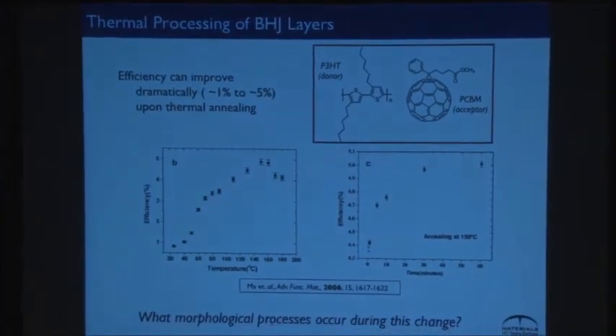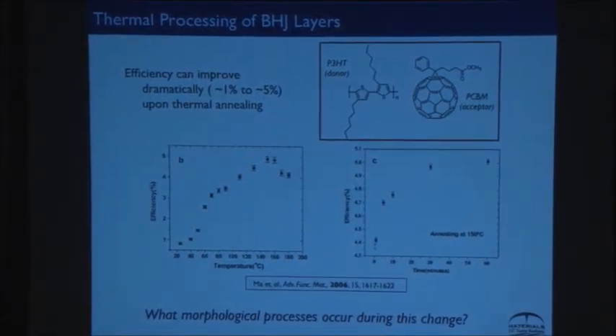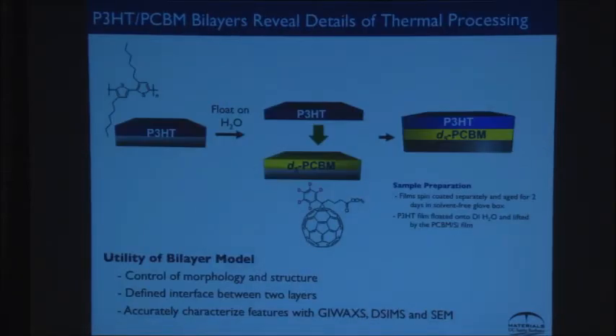For a long time, people argued about this, and they said, well, this material is crystalline, this one's not, maybe this one needs to order, it's impeded by the presence of the fullerene. It was tough to understand because you have this complex nanophase morphology. And so we came along a few years ago and said, well, this is too hard. Let's do something simple. So we tried to do a classic kind of material science experiment. At the time, people said that the fullerene wasn't very miscible because if you heat this thing too long, you'd get crystallites and see huge phase separation. But we were convinced that there was probably a little bit of fullerene that was getting into the polymer.